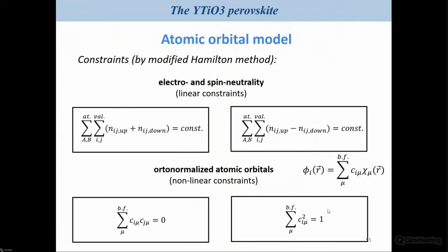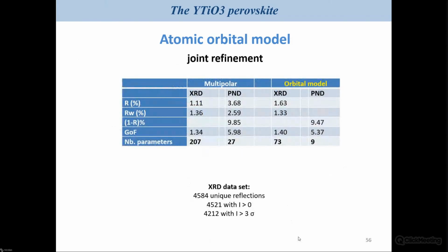But of course, again, you have to introduce constraints to be able to refine such a model: constraint for the electron neutrality, constraint for the spin also, and again the constraint on the orthogonalizations of the different functions you will use to describe the system. What is interesting if you use such a model is that you reduce a lot the number of parameters required for refinement. You see, compared to a multipolar refinement, you divide by 3 the number of parameters you need to consider for that modelization. So what is the result of such an approach in that case?